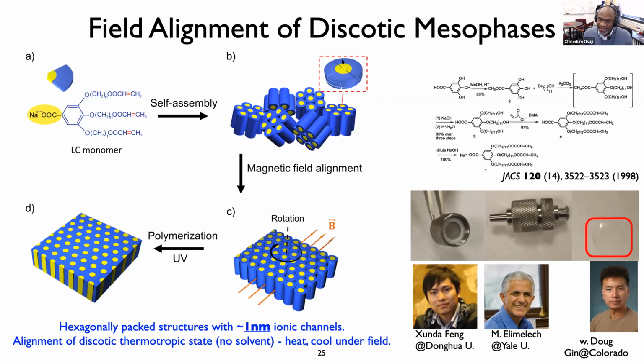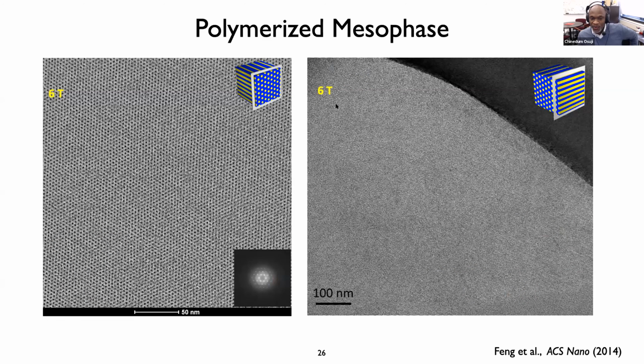And they're intriguing because at the center of each of these columns, in principle, is a roughly 1 nanometer diameter pore. And we approached Doug with an idea. My group had been very active in magnetic field directed self-assembly of block copolymers. And we thought, rightly, that we could use magnetic fields to control the orientation of these columns as a way to optimize the transport properties of the resulting materials. And in fact, we were able to do this.